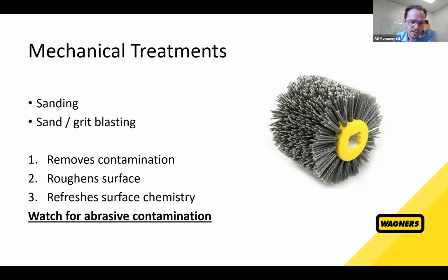Second thing is that it roughens the surface, as I talked about. And the third thing is that it actually refreshes the surface chemistry. If you're dealing with a thermoset type material like our pultrusion, sometimes the surface is quite inert because the resin itself is almost fully cured. So it's very hard to bond to aside from the surface energy. So if you abrade it, you can sometimes dig down and find a more reactive surface in terms of the chemistry in there. So mechanical, definitely don't rule it out if you're looking at something like that. It can do quite a few things, and it can definitely bring benefit to a bonding process.